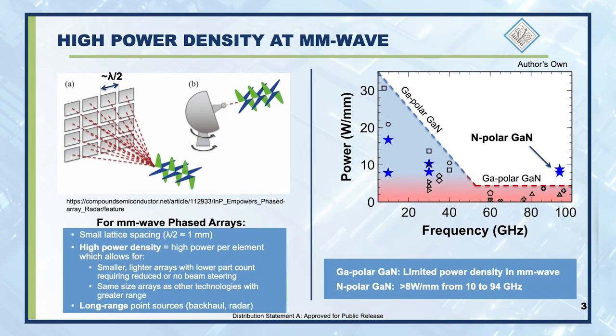Here I show the output power density of gallium polar gallium nitride versus nitrogen polar gallium nitride. You can see that as the frequency increases, the power density from gallium polar GaN decreases, shown by this line, and it flattens out at around 2 to 3 watts per millimeter at millimeter wave frequencies. Nitrogen polar GaN performs much better, 2 to 3 times the power density, 200 to 300% larger power density at 94 gigahertz relative to gallium polar GaN. This is an enormous advantage.